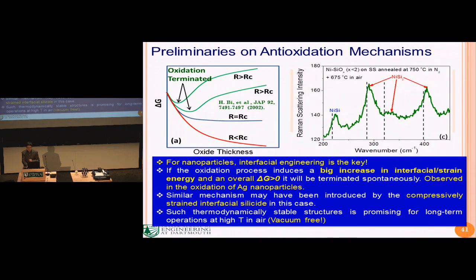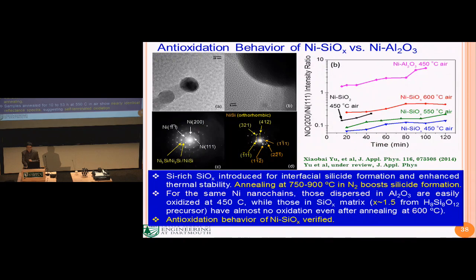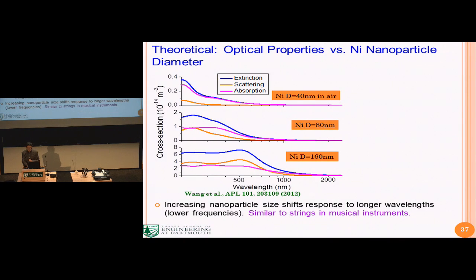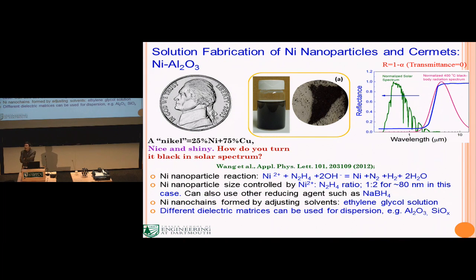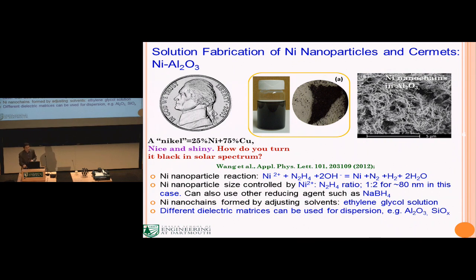Yes. So you talked about engineering them to change the size of the nickel nanoparticles. Yes. And that impacted the scattering and absorption. Exactly. But you described them as nanochains. You went really quickly. Oh, okay. A nanochain is forming like this. In this case, a nanochain can actually self-assemble if you use the correct chemistry, basically if you use the correct solvents in this kind of reaction.